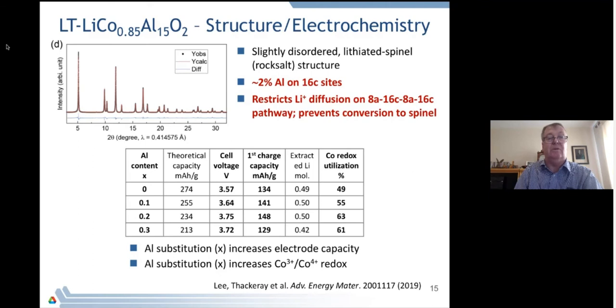except to say that some very elegant structural work has been done at the Advanced Photon Source by E.J. Lee. And the realization now is that the aluminium-substituted material contains what seems to be about 2% aluminium on the 16c sites, which then impacts the diffusion of lithium through the 8a-16c tetrahedral-octahedral site network for lithium diffusion. And this gives rise to the slight change in the electrochemical profile.